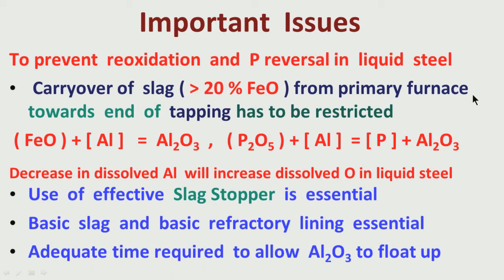So all these oxides, FeO, MnO, P2O5, can react with the dissolved aluminum in liquid steel. Where is the dissolved aluminum coming from? By the process of deoxidation, when you are adding aluminum, some amount of aluminum will be retained in liquid steel as dissolved aluminum, and the other portion of aluminum will react with dissolved oxygen and form alumina. And this alumina, we are trying to float up and get rid of. But if you have some carryover of slag from the primary furnace, then what is happening? This iron oxide, which is present in the carryover of primary furnace slag, will react with the dissolved aluminum in liquid steel. It will again generate some alumina.